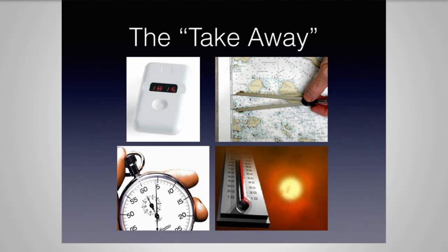And if your energy isn't sufficient and you're at a specific distance, the further away that you get, the more time you're going to need to cure in order to be sure to have sufficient curing of your composite. Otherwise, you don't know if you're creating a Tootsie Roll Pop, basically. Hard on the outside, chewy on the inside, which can then help to contribute to sensitivity and premature failure of your composite. So knowing what your energy level and knowing what amount of time that you may need is important.